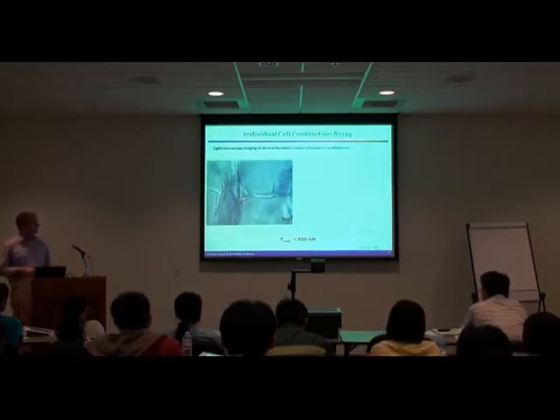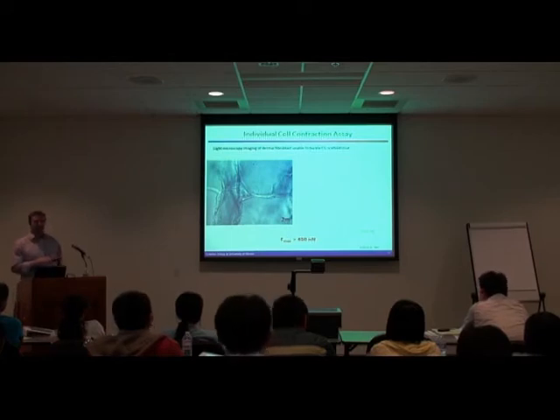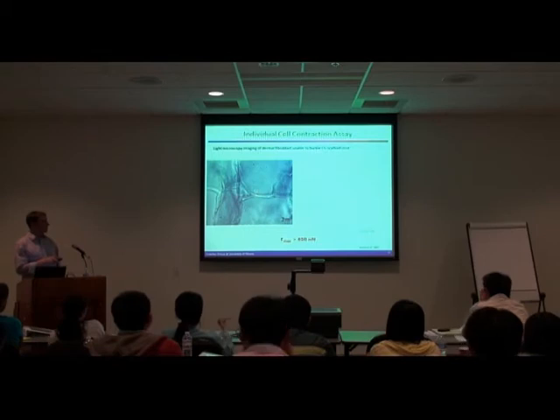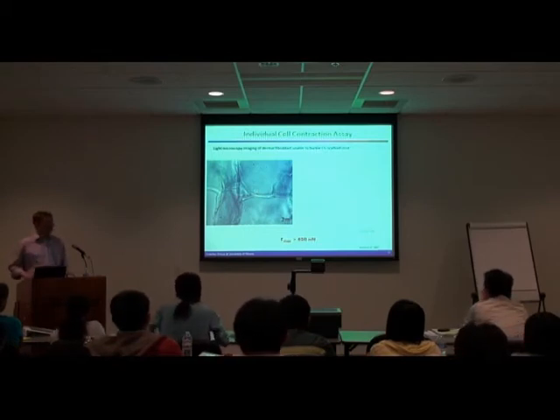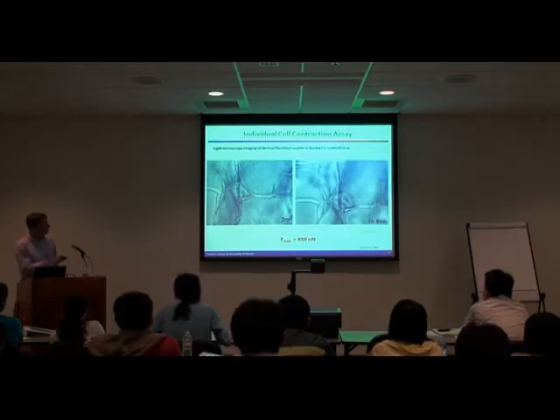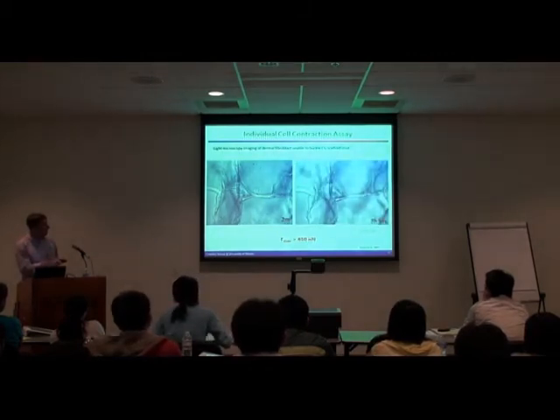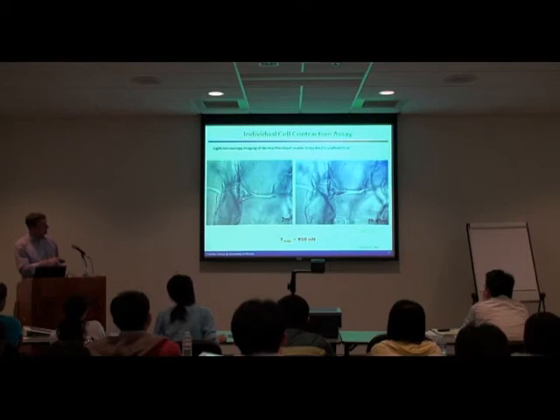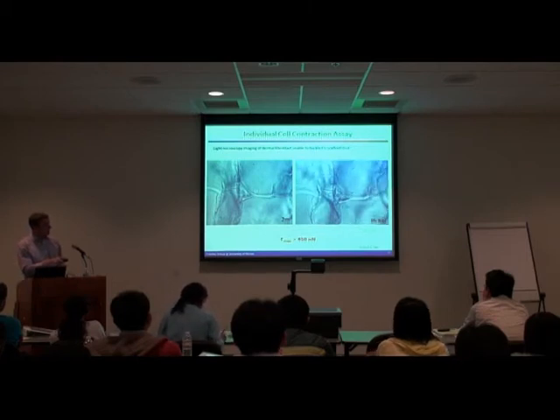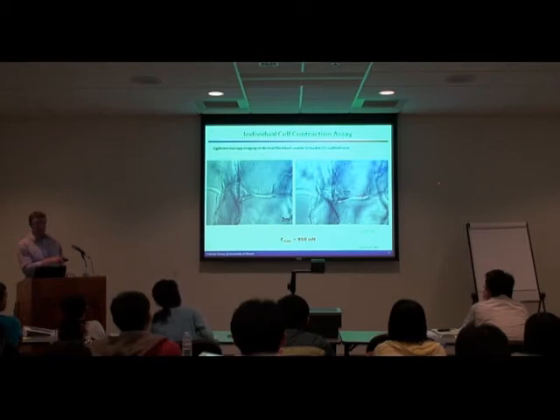In fact, one of the other things we noticed is that there were sometimes where cells couldn't buckle the scaffold. So we'd see some cells in a highly anisotropic scaffold that had some really thick, high-density structures within them. And what we saw is there's an individual cell that started rounded here. And over time, it started to elongate. And it started to generate some sort of tension within the cell, and that's the point where the focal adhesions actually sheared off and the cell detached from one side.